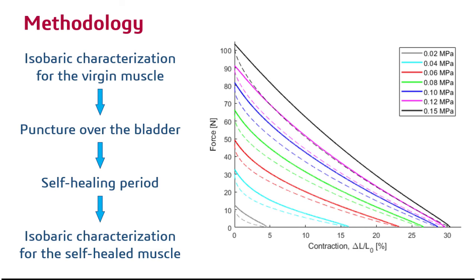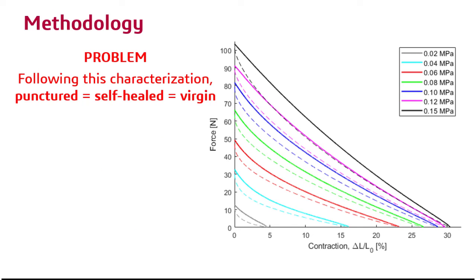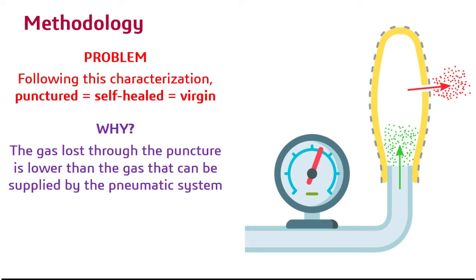The results for the virgin muscle are shown in this graph, which proves that our muscle works properly like any other McKibben muscle. However, with this characterization, we didn't notice perceptible differences between a virgin muscle, a self-healed muscle, and a punctured one. The reason is that the gas lost through the puncture is lower than the one that can be supplied by the pneumatic system to guarantee the pressure inside the muscle bladder. The input compensates the losses, so we couldn't verify whether the muscles were healed or not.